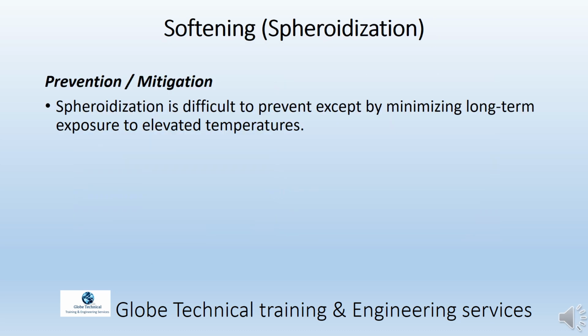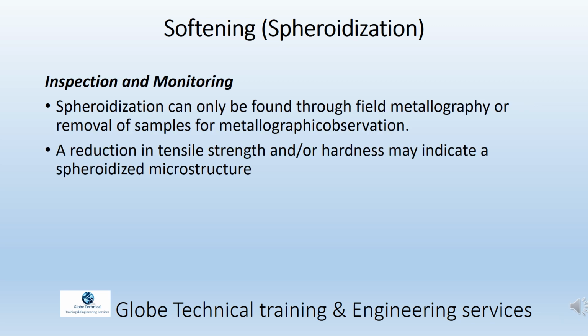Prevention, mitigation. Spheroidization is difficult to prevent except by minimizing long-term exposure to elevated temperatures. Inspection and monitoring. Spheroidization can only be found through field metallography or removal of samples for metallographic observation. A reduction in tensile strength and/or hardness may indicate a spheroidized